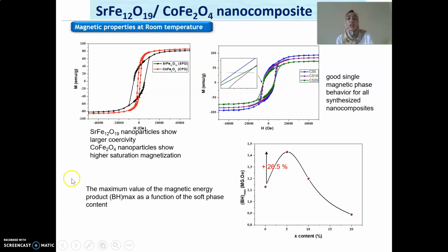As we can see from the parent hysteresis loops, the strontium hexaferrite has a larger coercivity, while the cobalt spinel ferrite shows the higher saturation magnetization. From the hysteresis loops of the nanocomposites, we clearly see that there is a good single magnetic phase behavior, which is a good indicator of the exchange coupling mechanism.